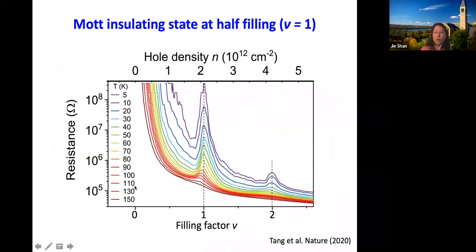Okay, so now let's take a look at some transport results. Resistance as a function of filling factor at different temperatures. At low temperature, you can see that there are two very pronounced peaks showing up. Unfortunately, at low temperature and low doping density, the contact resistance becomes very big. So we cannot get useful information out of this doping range. So the resistance peaks are at filling factor 1 and 2.